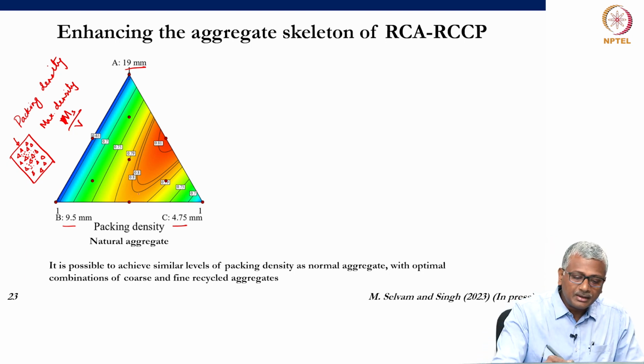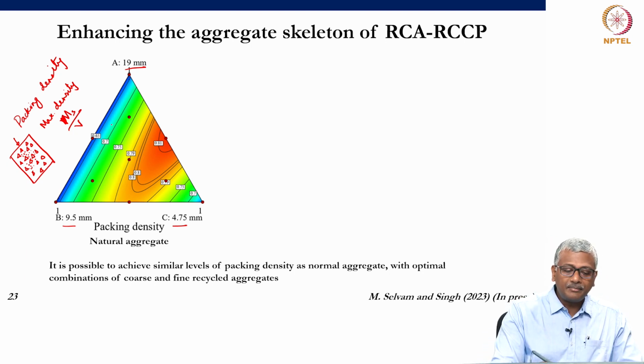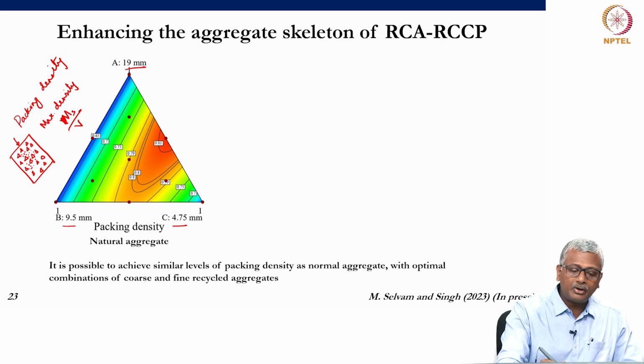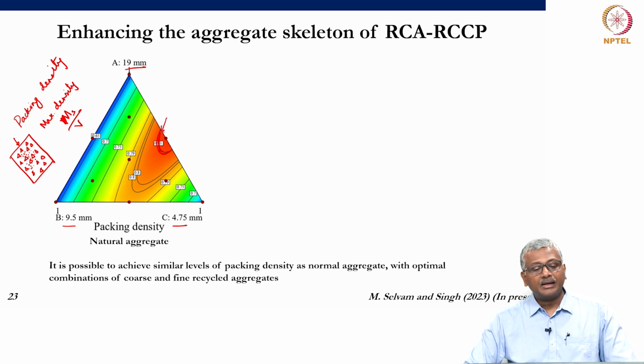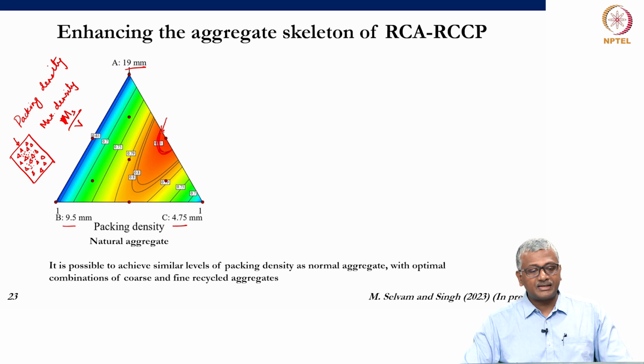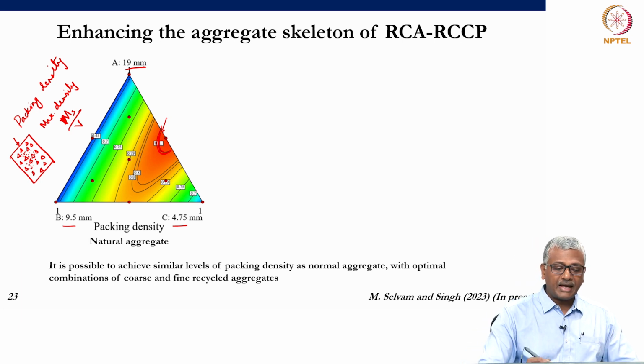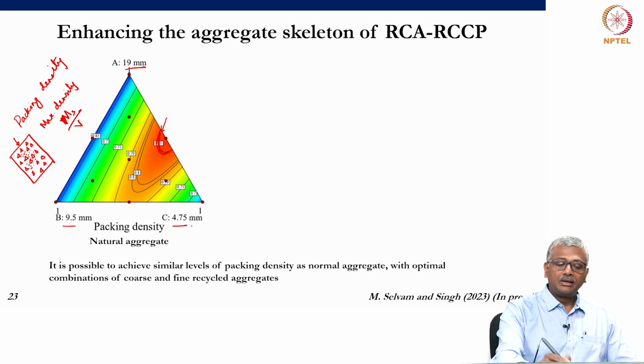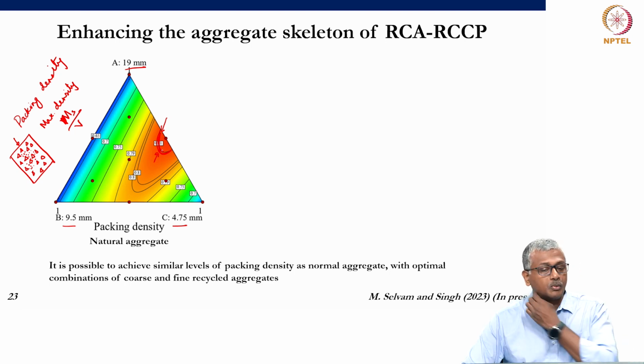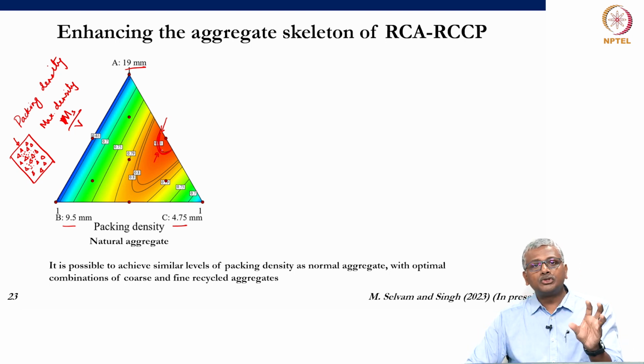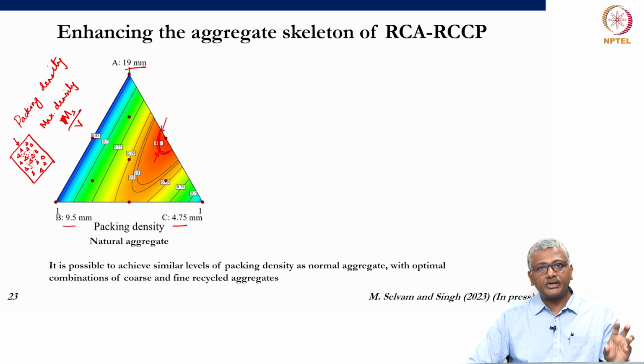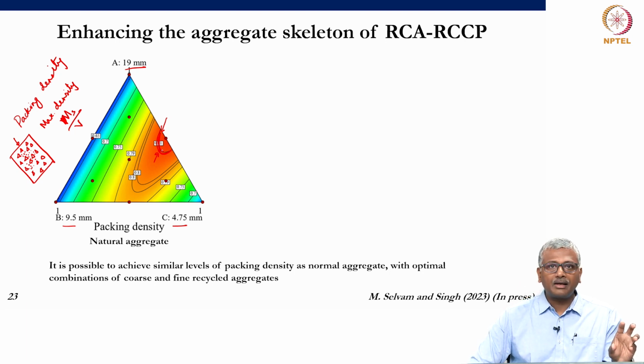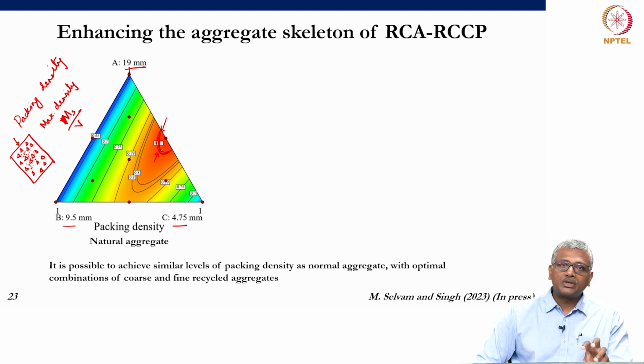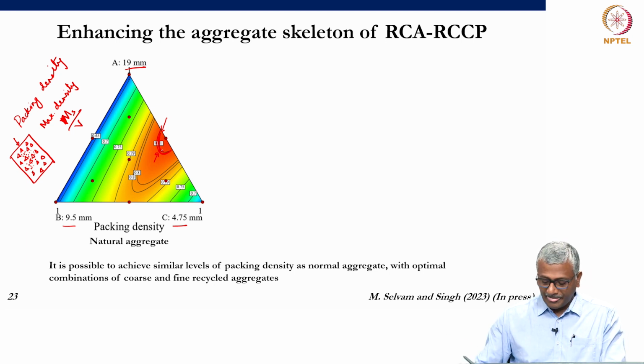And what you see here through this ternary diagram is that you are now able to achieve for certain compositions, you look at this 0.81 as the packing density, that is a contour of packing densities that can be obtained by combining aggregates in proportions which are leading to this packing density of 0.81. So, what you need to do is understand the particle gradation of your recycled concrete aggregate, design the proportion appropriately so that you get the maximum packing density.